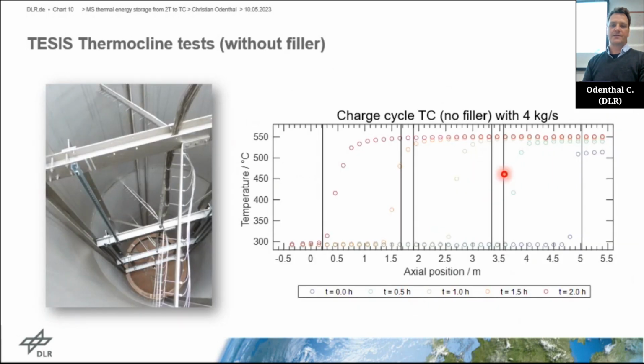Here you can see an example from our testing with a pure thermocline. We inserted a metal structure with multiple thermocouples inside the tank, where we measured temperature profiles on different axes, as well as, of course, along the middle axis. This was the first charging cycle during these experiments with a mass flow of 4 kilograms per second. That is the nominal mass flow we have in our plan.